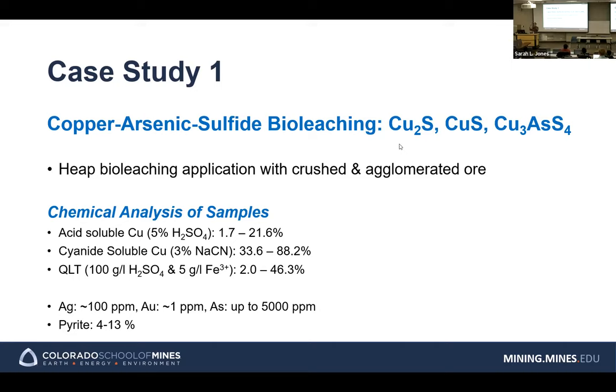So if you have material and you don't know how much chalcopyrite is in there, if you run the cyanide leach test and you have a high cyanide recovery, that means you don't have much chalcopyrite. But if you have a lot of chalcopyrite, your cyanide soluble assay is going to be really low. So this indicates chalcopyrite could be small, or sometimes I would say medium. So 33 to 88% cyanide soluble. So there is some chalcopyrite, but not a whole lot.